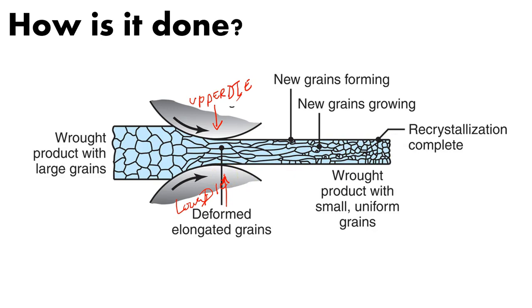And it can be a single die, it could be a series of dies, but you're actually changing the size and shape of the crystals, which in turn will actually give you much smaller grains. You're also going to get rid of a lot of the porosity inside of that metal as you go through the forging process. So you get smaller grain sizes, less porosity, but something else happens in this.